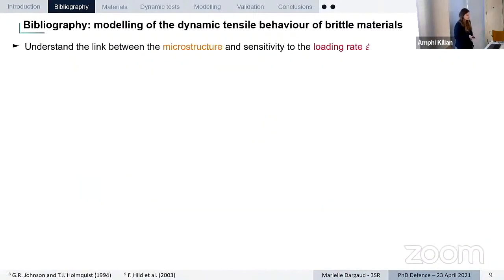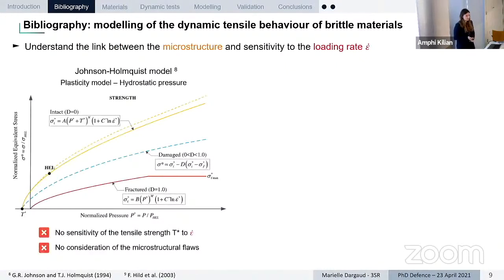When we look at the modeling part now in the literature, well, we have several models, but in our case, for brittle materials, we want to take into account the material microstructure and its sensitivity to the loading rates. So the most commonly used model to model a ballistic impact is the Johnson-Holmquist model, which is a plasticity model on which we impose a criteria of hydrostatic pressure. Even though it is very highly used, this model for confined compression and tensile behavior, there is no sensitivity of the tensile strength to the strain rate, and there is no consideration of the microstructural defects.